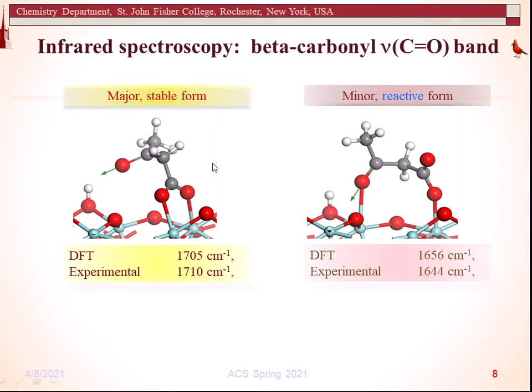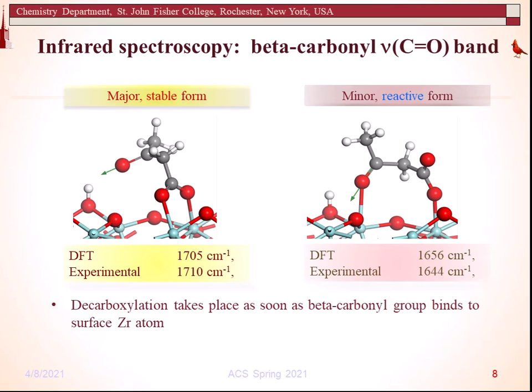The fact that the carbonyl group is not bound to the surface makes it stable against decarboxylation. When the carbonyl group binds to the surface, it makes the reactive form, which decarboxylates. DFT calculated values are in agreement with the experimental data.